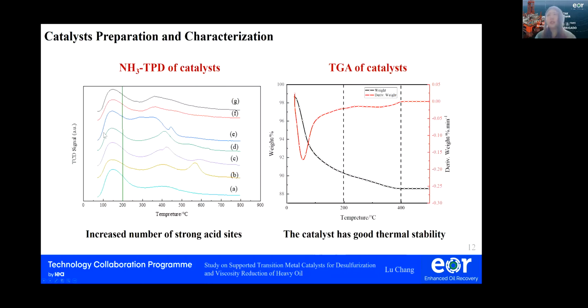We also did the ammonia TPD test. The graph shows that the surface of the carrier, which is line A, has many weak acid sites. And after the active components are loaded, the exit area and the number of strong acid sites increase in the high temperature zone, which is shown here. And the second graph is a TGA graph, which shows a good thermal stability of our catalyst.